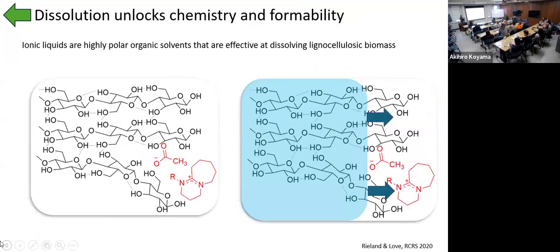So one of the mechanisms for this that I've been looking at is ionic liquids, which are highly polar organic solvents that can come in and break those strong polar bonds, the hydrogen bonds that link our cellulose together. And we can actually bring it into solution under fairly mild conditions, and I can dissolve trees. And we dissolve the tree, the wood, into this ionic liquid solution.